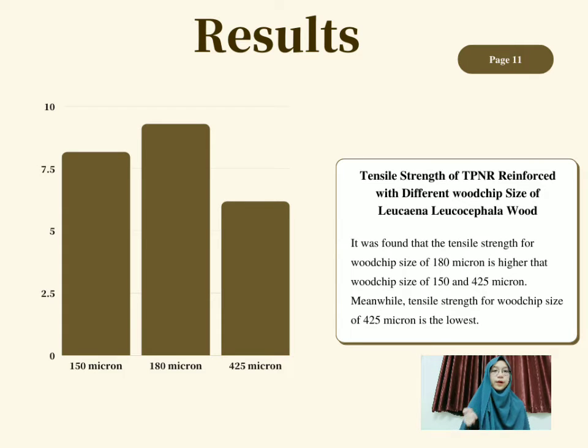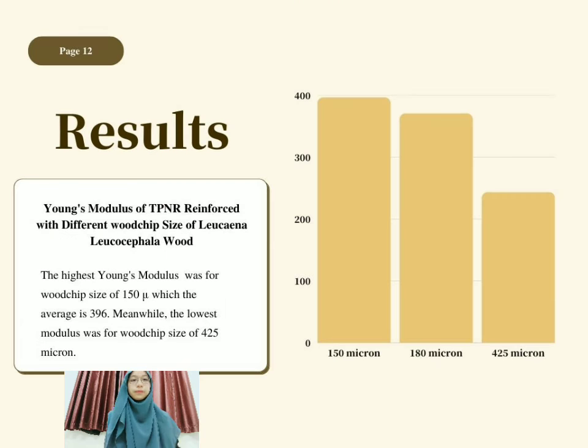Since the minimum requirement for tensile strength of TPNR is 4.68, thus the three sizes of Leucaena leucocephala woodchips meet the minimum requirement. As a result, the tensile strength for these sizes is 8.16, 9.29, and also 6.18. Therefore, for manufacturers, any of the woodchip sizes is suitable to choose, if they want to manufacture anything that requires high tensile strength.